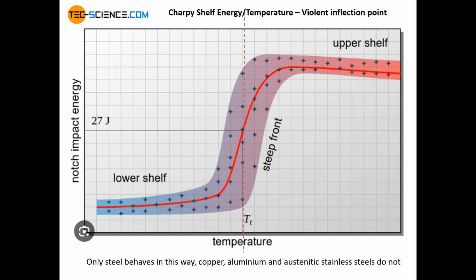But this property that steel has, which is a characteristic only of mild steel and cast iron, was not known at the time of building the Titanic. So when the Titanic hit the iceberg, the steel was at 0 degrees. It was subject to a high strain rate event, and it fractured. And that's why the Titanic broke in half and sank. Only steel behaves in this way, which is an important thing to remember.